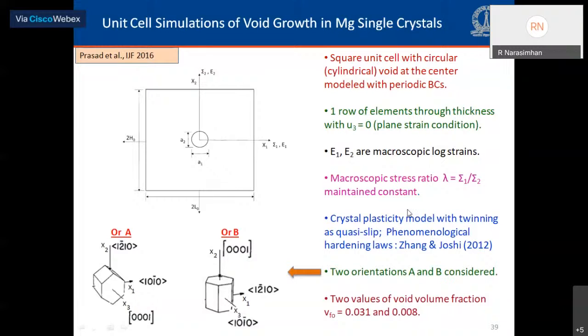And in these simulations, we make use of the crystal plasticity model, which I described earlier, along with those hardening laws I mentioned. Two different lattice orientations were modeled. In orientation A, the C-axis is along the out-of-plane direction, that is the thickness direction. In the case of orientation B, it's along the maximum principal stress direction, X2 direction.